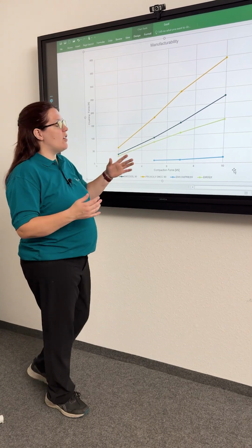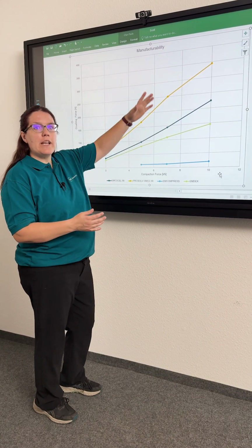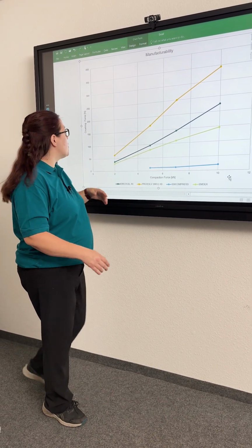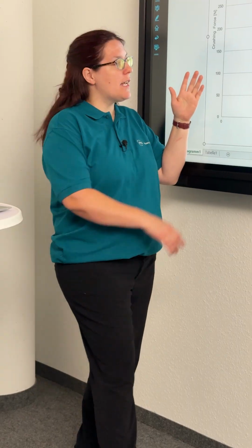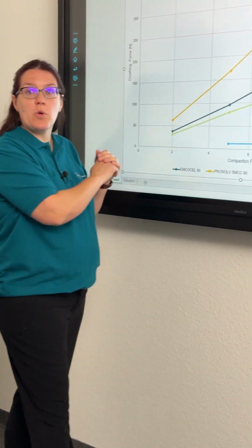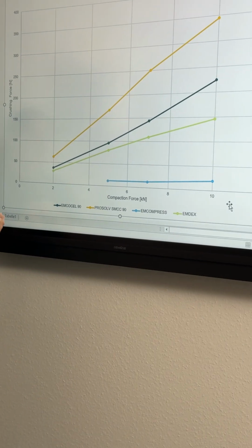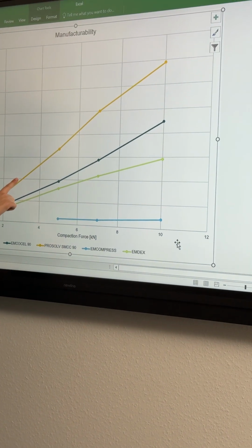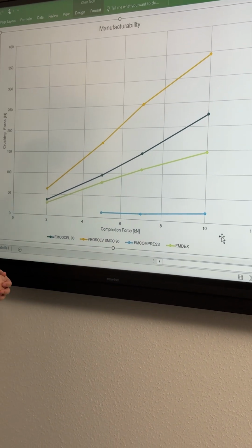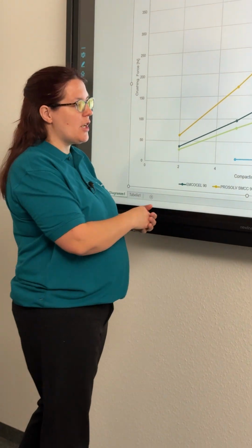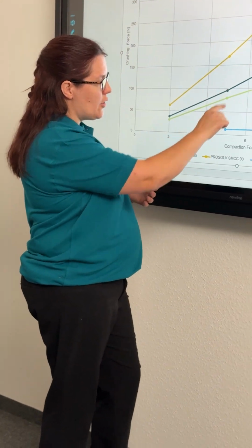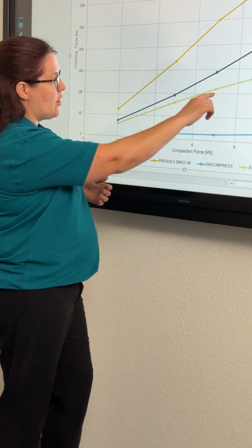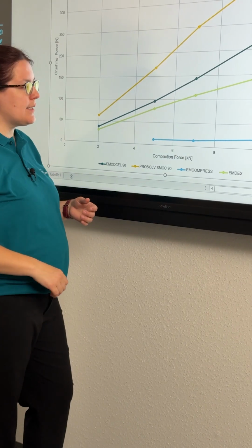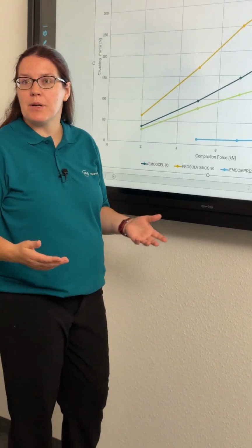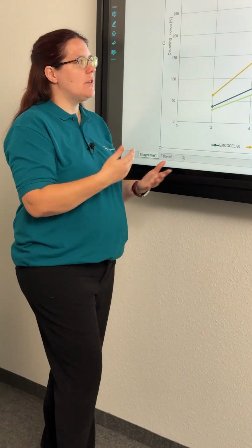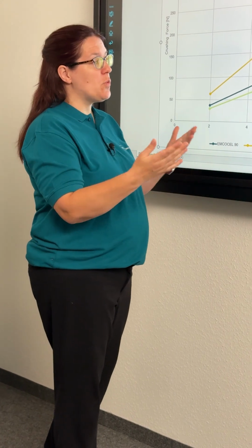So if instead of taking a compaction force and looking at the difference in tablet hardness, you choose a tablet crushing force and you look at the amount of compaction required to hit that target value, you can see that with the SMCC, maybe 3 kilonewtons is sufficient to hit that target hardness, whereas for MCC, you need 5, MDEX, you need a little more than 6, and actually you never achieve it with M-compress alone. So this has a couple of advantages. One is